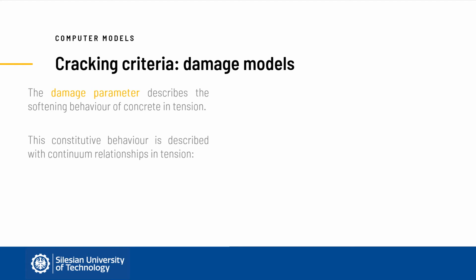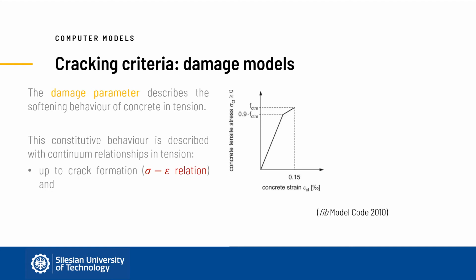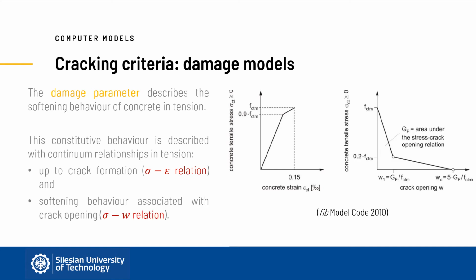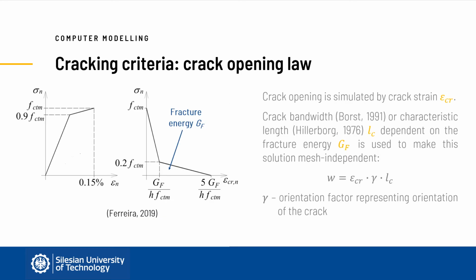The constitutive behavior of concrete in tension in the damage models is described by two relationships. Stress-strain relationship before cracking, which for concrete is usually defined by a bilinear relationship, and the softening behavior after formation of the crack associated with the crack opening. In smeared cracking models, in which the crack is not physically represented, the crack opening is simulated with the so-called crack strain. The width of the crack can be then calculated from the value of this cracking strain. To make this solution independent of the size of the mesh, which would otherwise impose the location of the crack and its development, the characteristic length, also called a crack bandwidth, is used, which depends on the fracture energy of concrete.